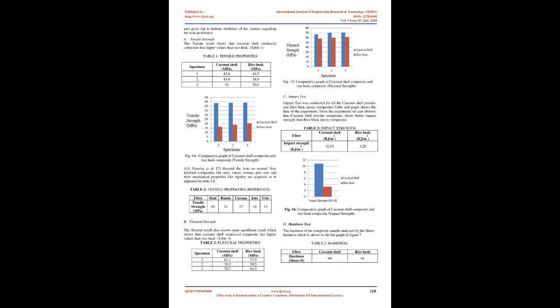A. Tensile test. The tensile test is the most commonly used test to assess the mechanical properties of materials. The tensile test is done on the ASTM D638 test standard, Fig. 6, with an extended load applied at the 2 ends. The test specimen size was 165 mm x 19 mm x 6 mm. B. Flexural test. The flexural test specimens, Fig. 7, are prepared according to the ASTM D790 standards. The 3-point flexural test is the most common flexural test and is used in this test for checking the bending strength of the composite specimens. The test specimen taken is 120 mm x 12.7 mm x 6 mm. 2 parallel rollers support were used to support the specimen, and load was given using the loading nose.